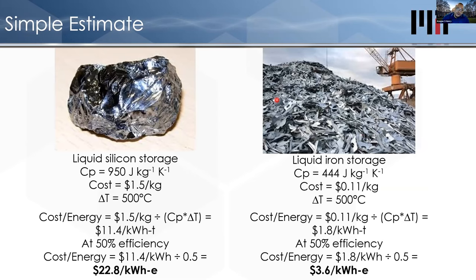If you imagine trying to store energy in something like liquid silicon, you take the heat capacity and cost of metallurgical grade silicon, which is about 98% pure, at about $1.50 a kilogram. Imagine you store the energy in the sensible heat of silicon, meaning you take silicon, let's say it's already liquid, and you heat it up to another temperature that's 500 degrees hotter. You put in energy to do that, and then you can extract energy when you let it cool back down 500 degrees. If you cycle it in that way, the cost per unit energy would come out at about $11 per kilowatt hour, but that's thermal energy. If your conversion is about 50% efficient, that's a factor of two higher. That's about $22 a kilowatt hour electric.